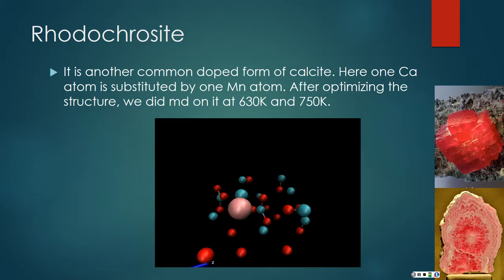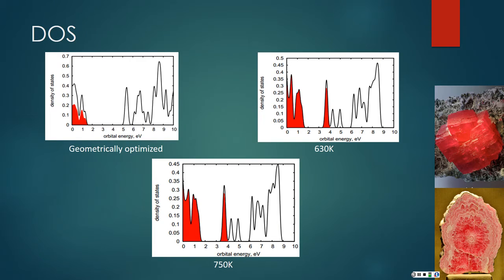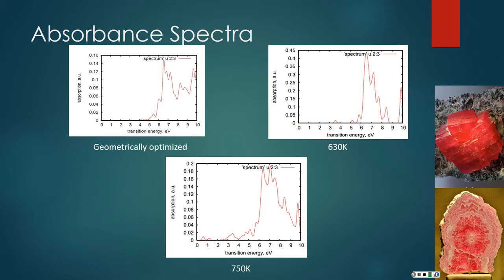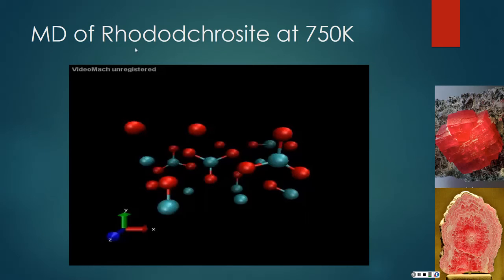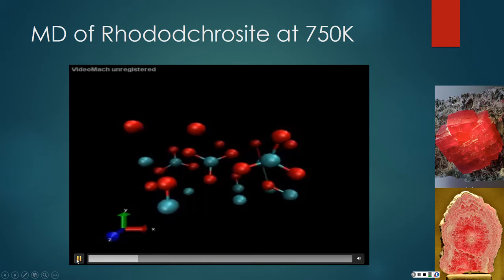And that's another form of the doped calcite. It is rhodochrosite, and we did the simulation at 630 Kelvin and 750 Kelvin. If we look at the DOS diagram, we can also find that the HOMO-LUMO energy gap is increased with the increment of the temperature. And if we look at the absorbance spectra, we can find that the orbitals are separated into two regions, and the d-d transition is less intense or almost vanishing here. So that's the MD of rhodochrosite at 750 Kelvin.